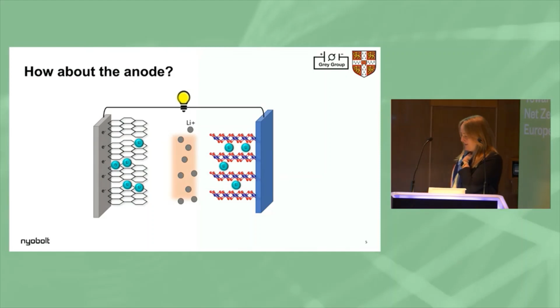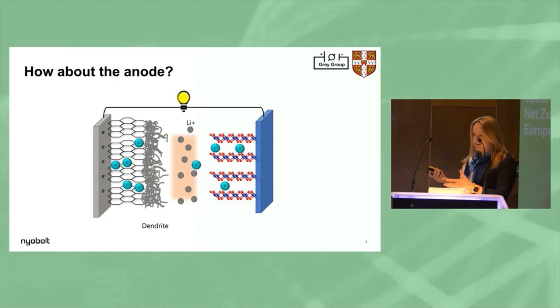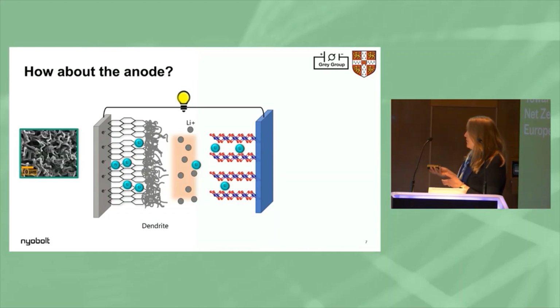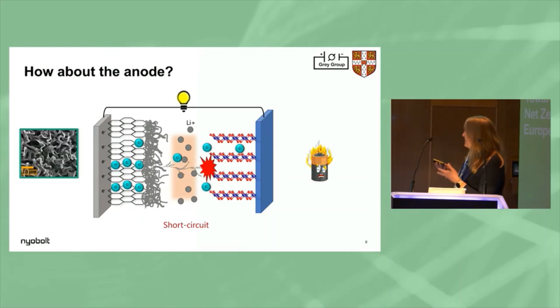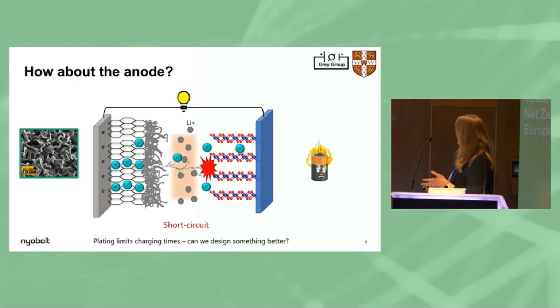But if we look at the anode, so typical materials such as graphite shown here, as we charge the battery, the lithium ions move into the structure. And as we charge more quickly, they build up on the surface, we get plating, and this can form dendrites on the surface, which can, as it builds up, penetrate through to the cathode, get short circuit, thermal runaway, not a happy battery. So we're limited on charging times by this phenomenon.